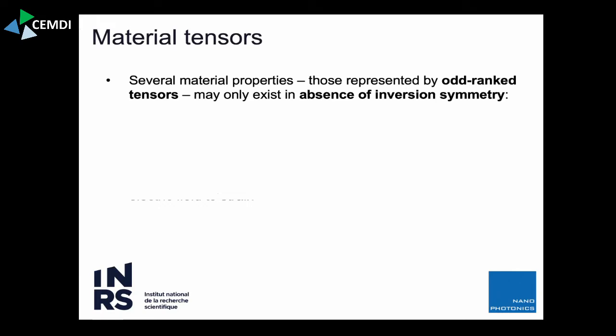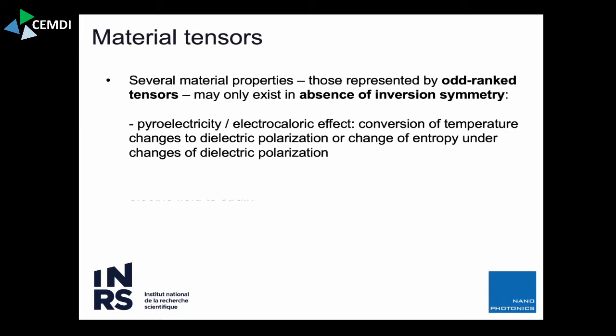To remind you of some of those, there is no pyroelectricity and no electrocaloric effect, which is the change of the electric polarization dipole moment under changing temperature, which is in all motion detection systems. If you have a center of inversion symmetry, it doesn't work. The other way around, electrocaloric, a bit more recent, is the conversion of electric fields into changes of entropy. The other one, a little bit better known here, is second harmonic generation, which also relies on the absence of inversion symmetry. And I'm going to use that in a moment.